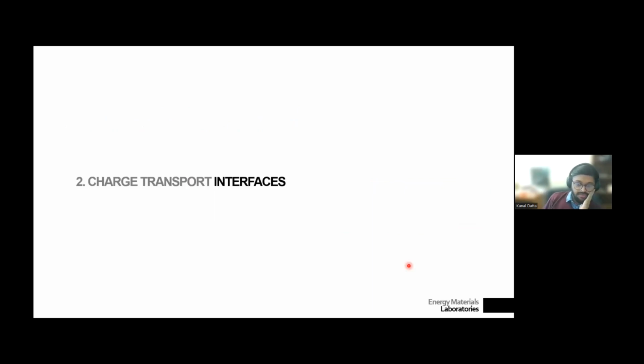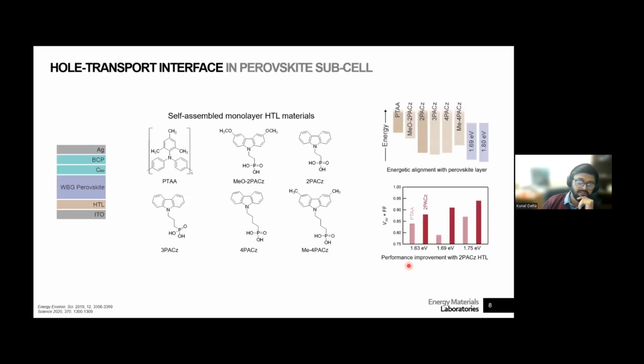So I would then discuss transport interfaces in these perovskite subcells, and specifically I would focus on the wide bandgap device. The first thing, and this has been the subject of a talk from a previous speaker at this forum, that we looked at in these devices was the self-assembled monolayers, and that's to do with the hole transporting contact. So this is the general device architecture, and these are the molecules that we looked at. PTAA was standard at that time, and these molecules were starting to come up. These three were commercially available, and these two were synthesized in-house.